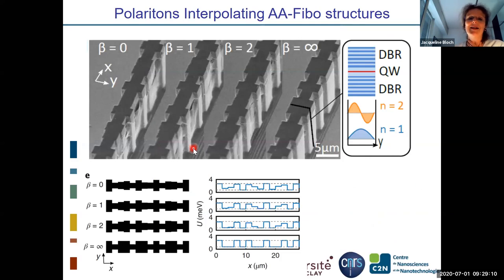To do that, we made modulated wires, using this perturbation approach. You see here wires, the top view of the wire, and this is the potential that it implements. This is the Aubry-André potential. Then you see different wires for increasing values of beta, and here, this is the Fibonacci potential. They look quite similar, but these very small changes in the shape of the wire dramatically change the localization properties of your polaritons.